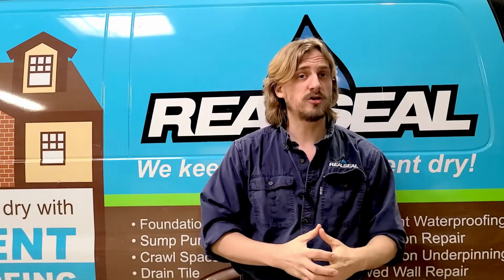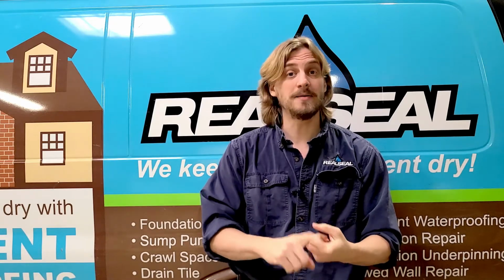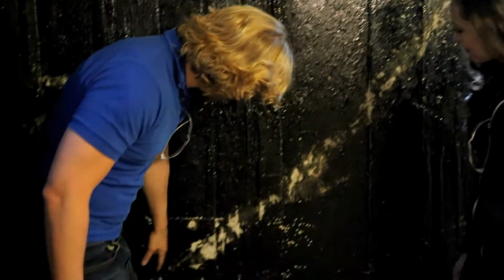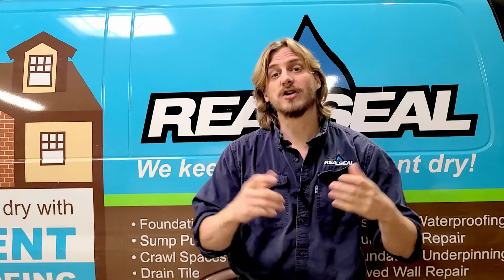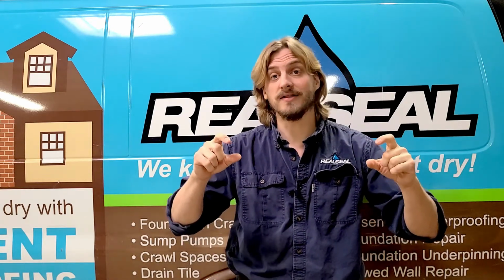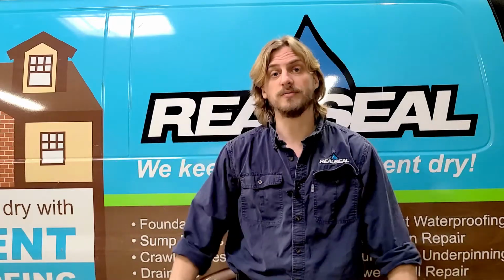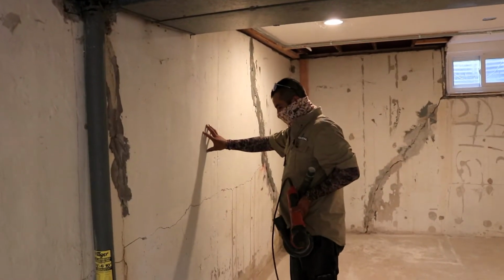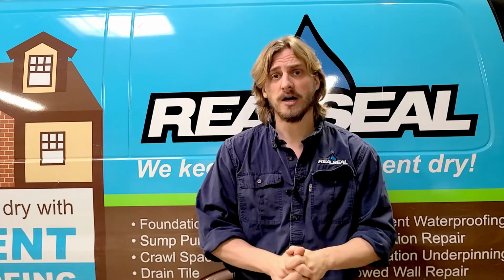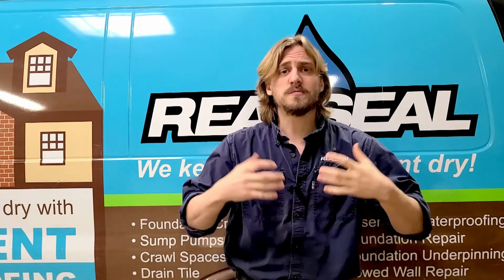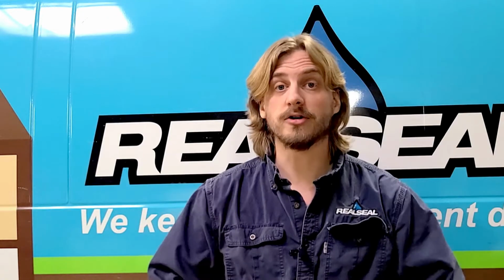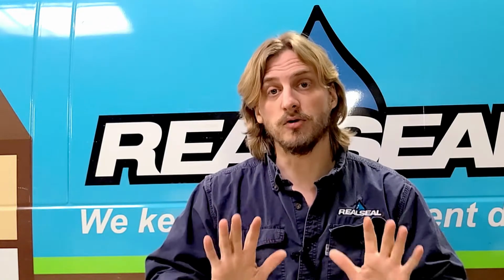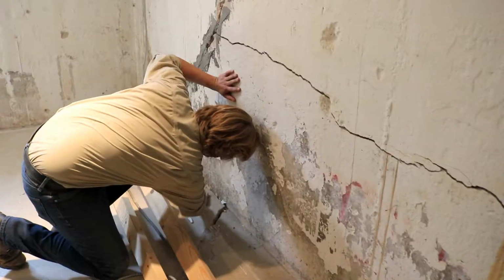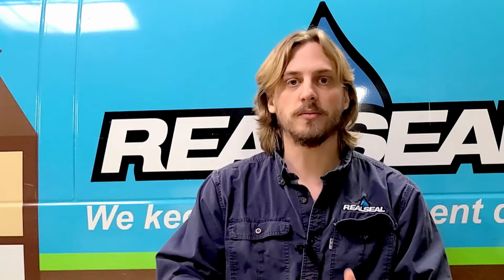Other ways that foundation cracks can form are off of stress points like I-beams or windows, or door frames set into the foundation. These stress points have higher load weights than in the other areas where the foundation is full from top to bottom, and so they can cause stress fractures. Another way that cracks can form is from hydrostatic pressure, which is basically water building up outside or underneath the foundation and causing it to move and crack. When your home settles over time, these cracks can form more in a structural kind of nature that require a bit more repair than just a simple epoxy injection.